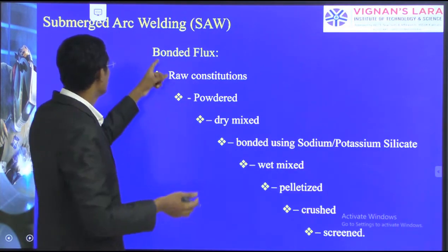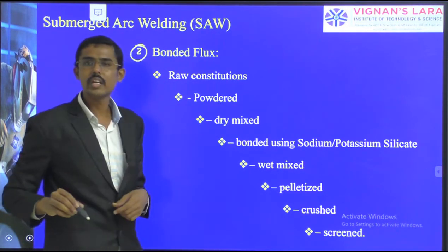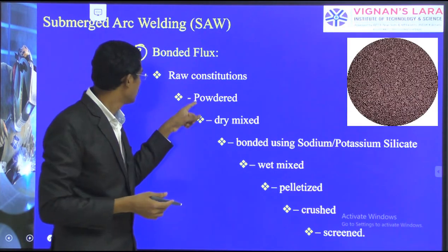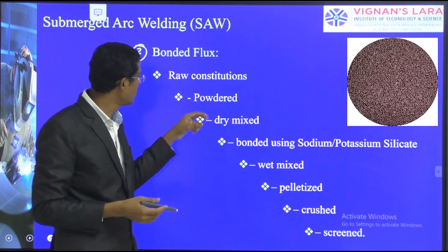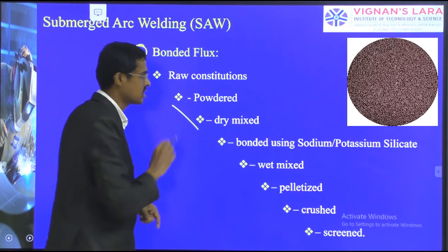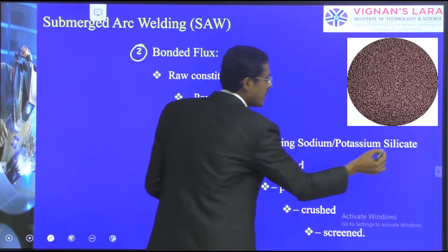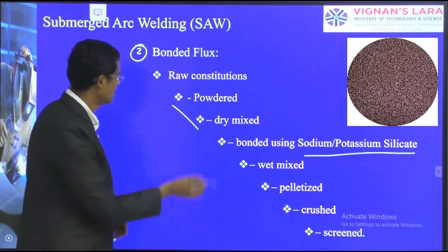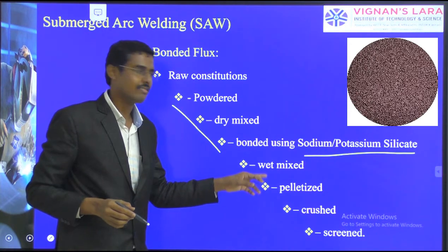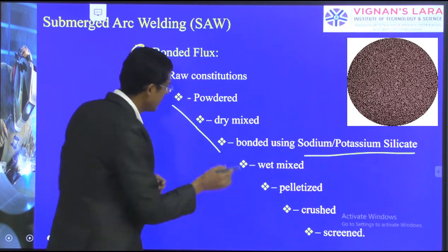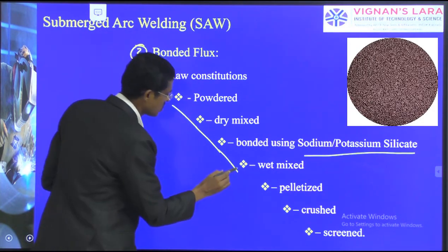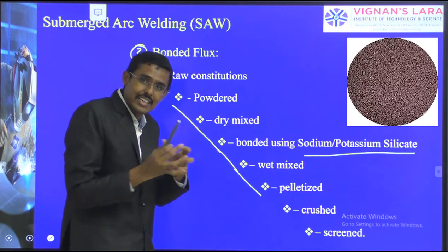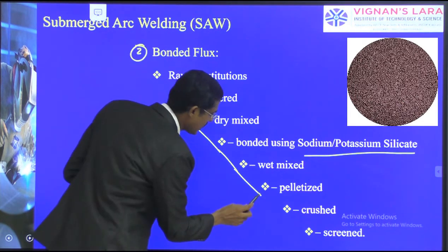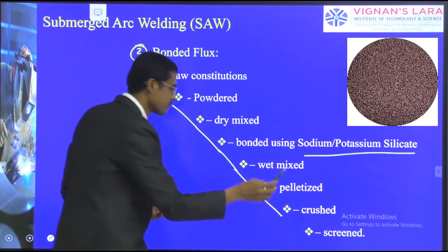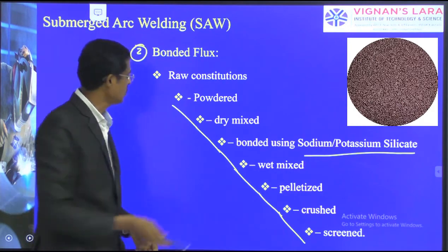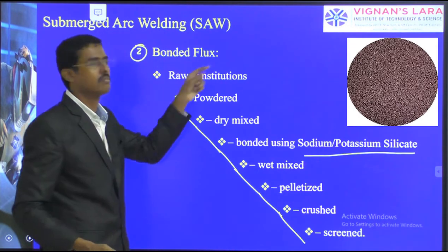The second method is the bonded flux. Similarly, we take the raw constituents, all in powder, and mix them in the dry powder form. Then they are bonded using sodium and potassium silicate as a binder, so it is wet mixed. Then it is pelletized, and later crushed again for finer granules. Then again it is screened size-wise and graded. So this is the path of preparation of the bonded flux.